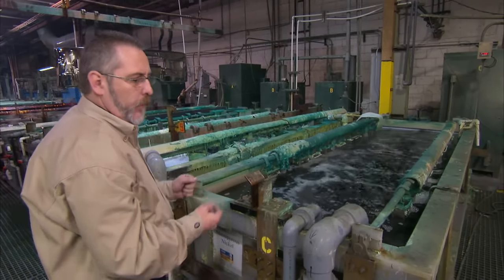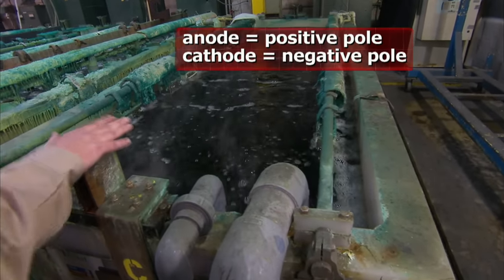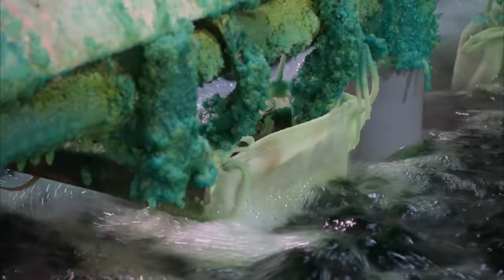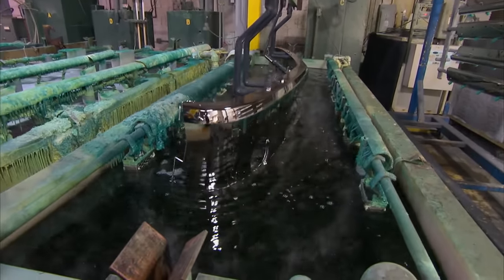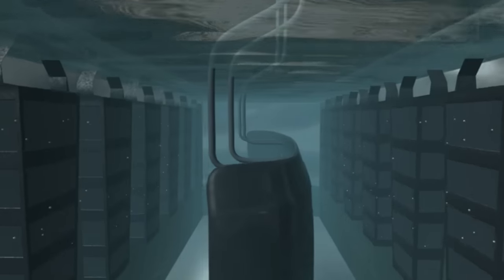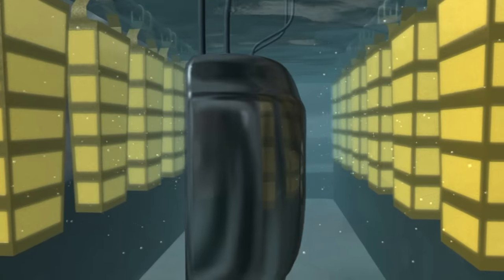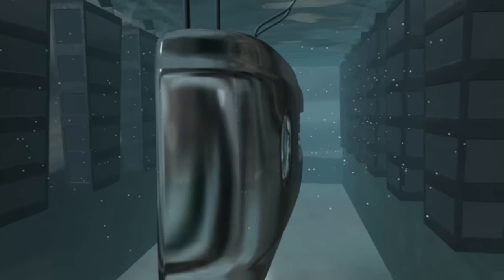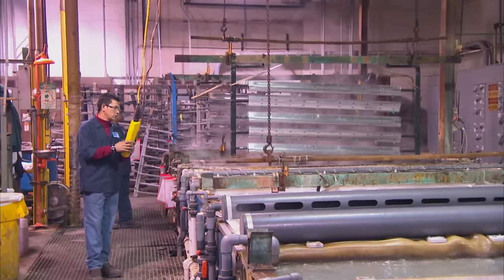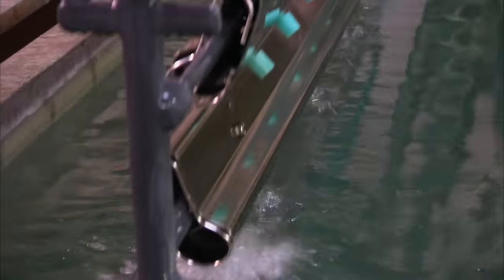You have your positive hookup on both sides, which is your anode; the cathode, or the part itself, is negative. The hanging baskets on each positively charged side contain the metal to be plated. The 2,500-gallon tank is filled with an acidic solution that permits the flow of electricity. Since the part is negatively charged, it attracts the positively charged metal from the baskets. In their large-scale electroplating line, truck bumpers and step tubes travel back and forth for more than three hours between 28 tanks.